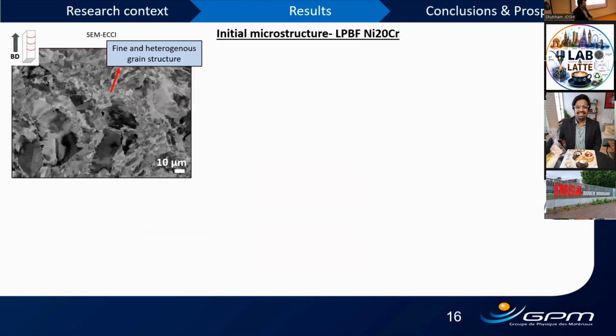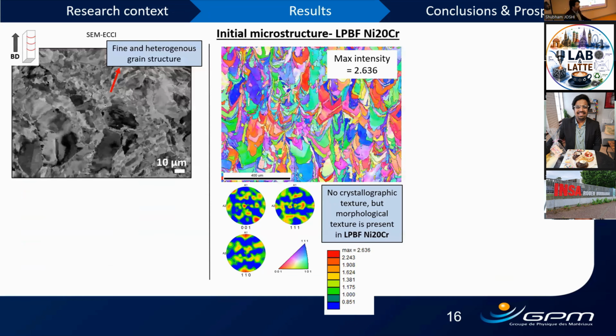Looking at the initial microstructure now of LPBF nickel 20 chromium, this imaging has been done in SEM ECCI, and the building direction is upwards, and we see a typically formed fine and heterogeneous grain structure. If we look at the grain orientation map, we see the melting pools like this, in this orientation, the building direction going upwards, and the maximum intensity to be 2.6,